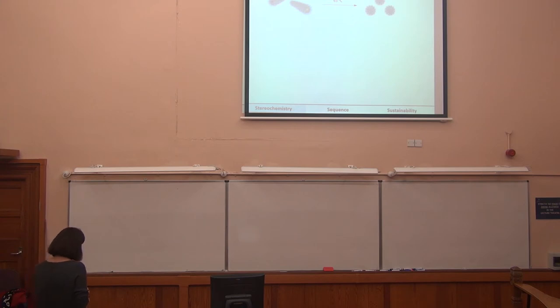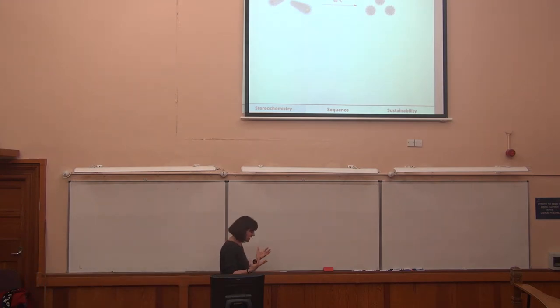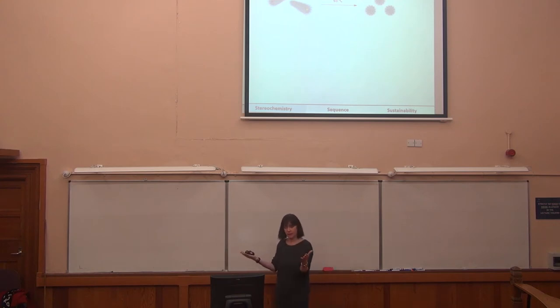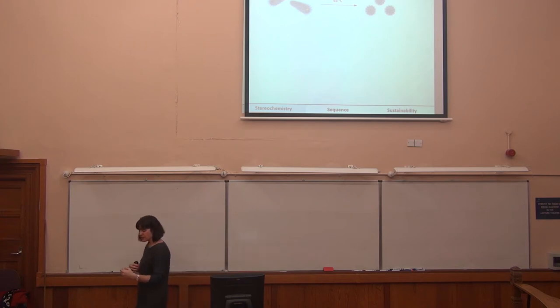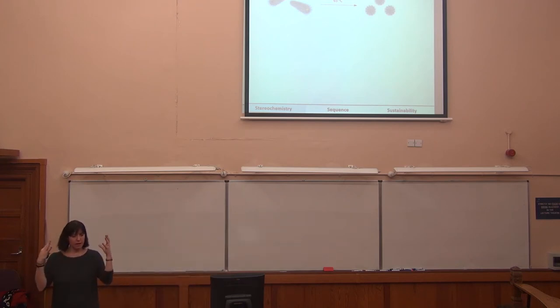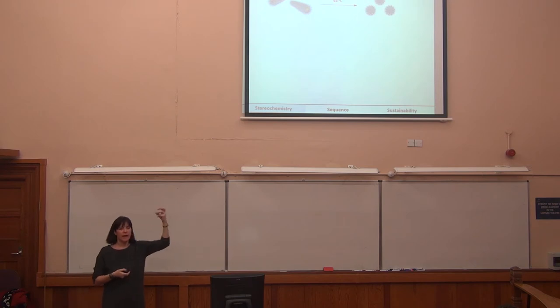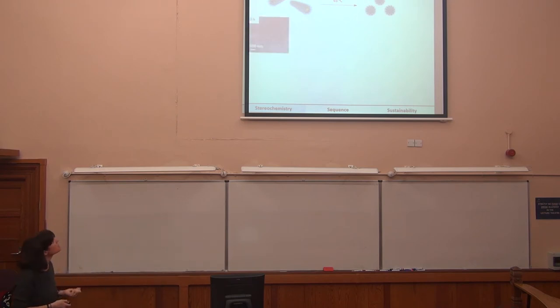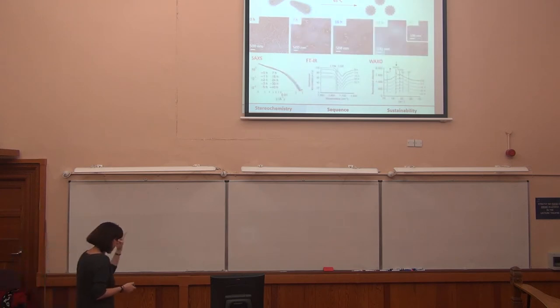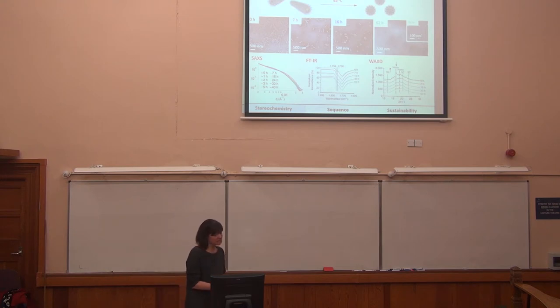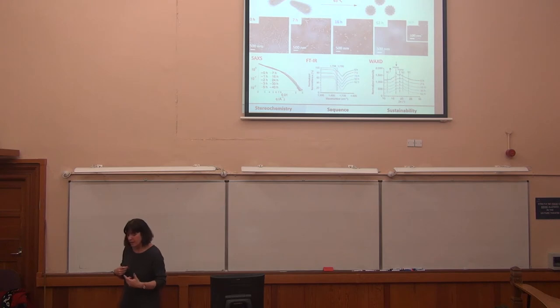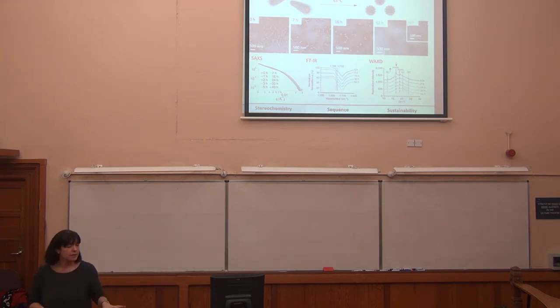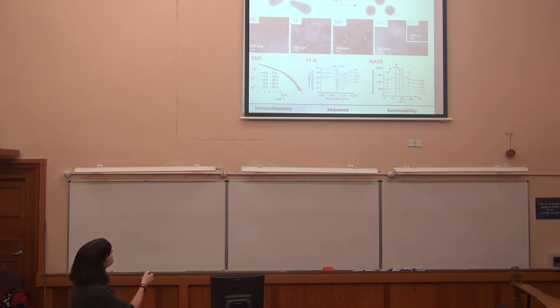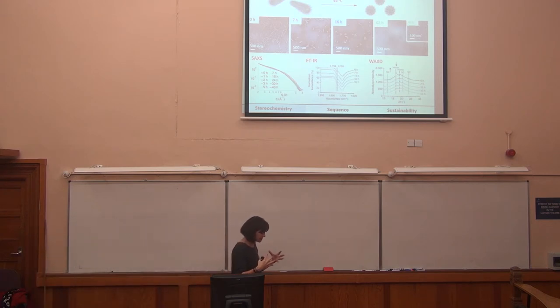But what we were really quite interested in is, could you imagine having two cylinders with potentially two different actives in them, and if we mix them together, over time they were able to reorganize and reassemble into, say, a spherical construct, we'd be able to get a triggered release. And rather than having a delivery vehicle where you have a particle that then goes to a polymer that then dissipates, we would still have a defined particle in our system. And this works, it actually works, it's slow, which with some of the work that we're now starting to do in a more biologically relevant context actually means it's probably quite a good thing. We can get quite a slow release of two different components, which can then trigger a much faster cascade. But with these initial results, we can see that we use a lot of small angle X-ray scattering, FTIR and WAXS, to be able to show that we can change from these isotactic systems through to the stereo complex.